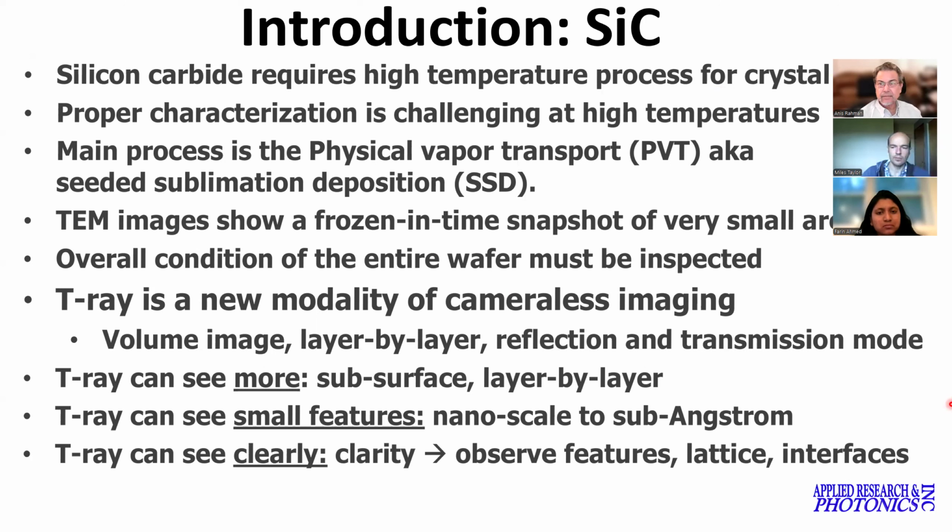Also, the other thing is the temperature. Silicon carbide will be functional at higher temperature compared to silicon. Silicon will give up a long time ago. So those are the two, as well as the other thing called radiation tolerance. Three very important quantities. One is the high voltage, one is the high temperature, and the third one is the radiation. So if you have a circuit inside a nuclear reactor, for example, where there is a lot of radiation, is it going to still work or give up?